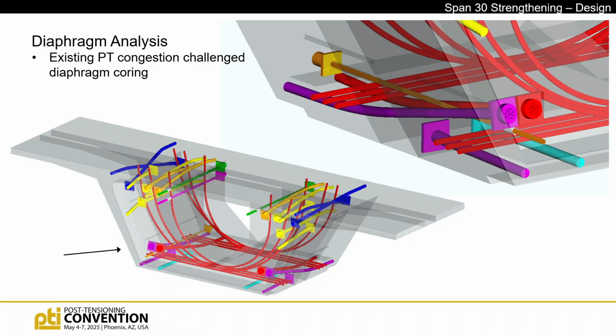The orange tendon here had to be cored between 2 existing bottom slab tendons. Now, we benefit here that we did have an erection PT bar hole that was in that location. So we knew where those tendons weren't, but that PT bar hole was not continuous through the diaphragm. Remember, there's a 2-foot closure pour in the middle of it, and the holes don't line up. They were several inches off. Yeah. So, but that did help us in guiding between those 2 tendons.